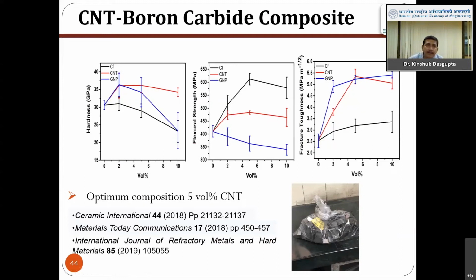But with carbon nanotube, the hardness almost remains the same. It does not come down unless at high percentage, where agglomeration takes place. But for graphene nanoparticle and carbon fiber, it deteriorates because these are soft phases. Graphene as well as carbon fiber are soft phases, and they decrease the hardness.